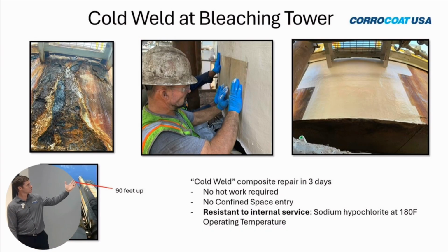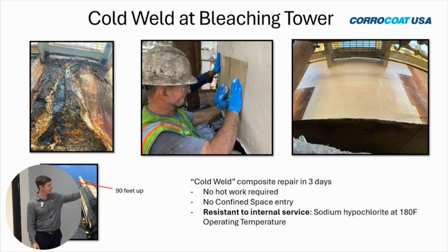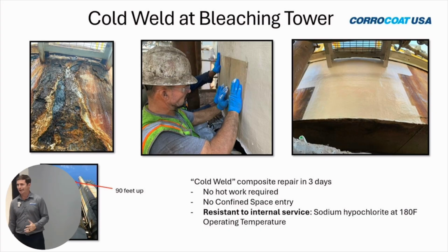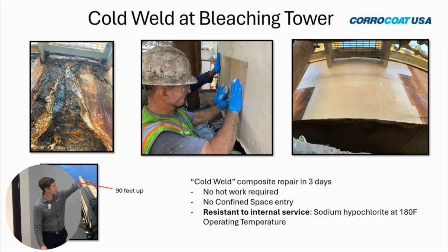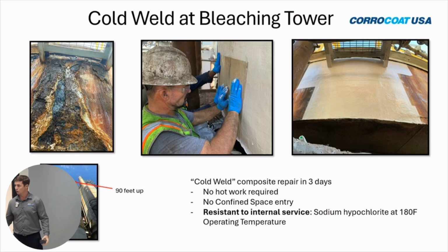We can use cold welds. So this is a project that we did 90 feet up at a pulp and paper mill in a bleaching tower. The bleaching tower had 10% sodium hypo at 180 degrees F, which is 80 C. It was a tile lined tank. The tile failed, and they had a gaping hole here up at the top. They had a short outage. They had other work going on in the area. They couldn't do hot work, like a lot of your plants don't like hot work.